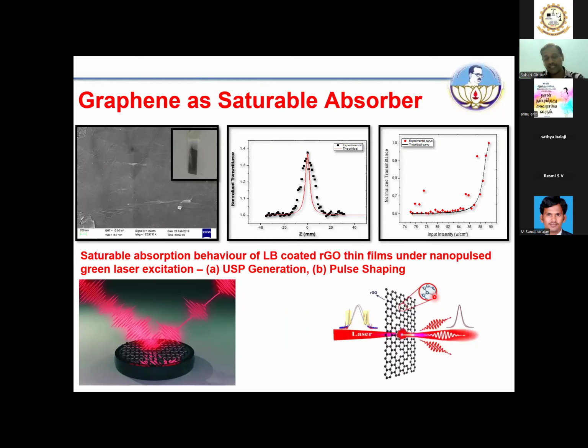So with that, I will quickly go to the material discussion, what we have done in our laboratory. I will just give you two or three quick examples. If you look at the literature, you will see graphene is basically a saturable absorber. So when you perform a Z-scan experiment, it gives a peak-like pattern, which says your graphene is a saturable absorber.